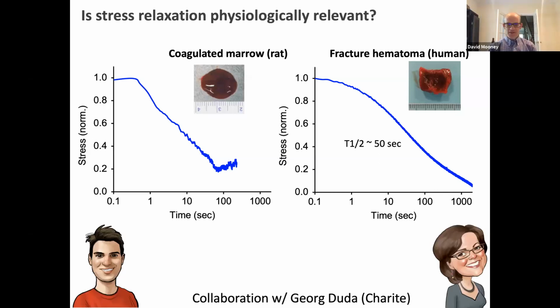So Max Darnell, who's now doing a postdoctoral fellowship out at University of Washington, and Evie Lippens in the laboratory of our collaborator, Georg Duda at the Charité Hospital Berlin, mechanically characterized two environments in the body where bone regeneration normally occurs: coagulated bone marrow following a break, and then fracture hematomas from human patients that were coming back for revision surgeries. And what they found is that these tissues are basically viscoelastic and exhibit timescales for relaxation that were very similar to what we empirically found to be optimal for osteogenesis.